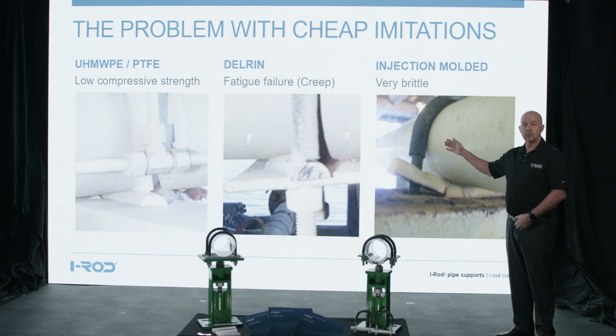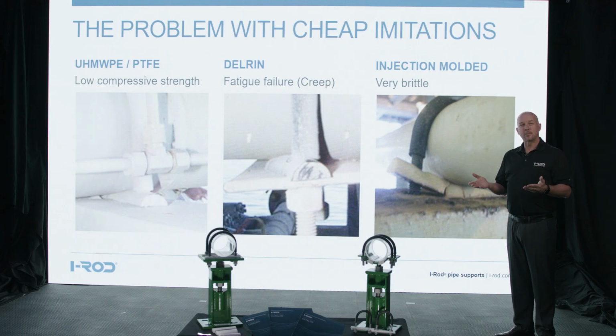In the center here is Delrin. Delrin is usually black, but not always. You'll see here that not only is it smashed down, it's completely deformed out of shape. It's curved and completely deformed because Delrin is softer than the other two materials over here. Just doesn't work very well. And then on the right here, the last one, this is injection molded plastic. It's a very brittle material. You can't get the same compressive strength by injecting plastic into the mold as you can by extruding the plastic from a machine, which is how our iRod and these other ones are made.